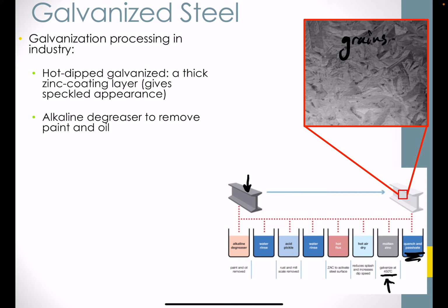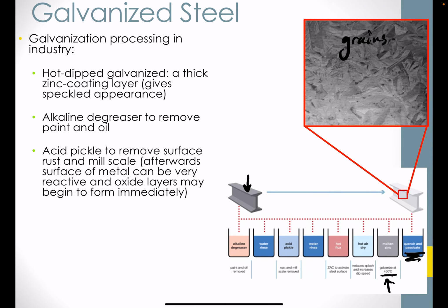So the first step here is an alkaline degreaser to remove paint and oil and other sort of surface contaminants. Second, there's an acid pickle. So this acid dip step here removes any rust, any oxides. Typically oxides are soluble in low pH acid. And this readies the surface to receive a zinc coating.